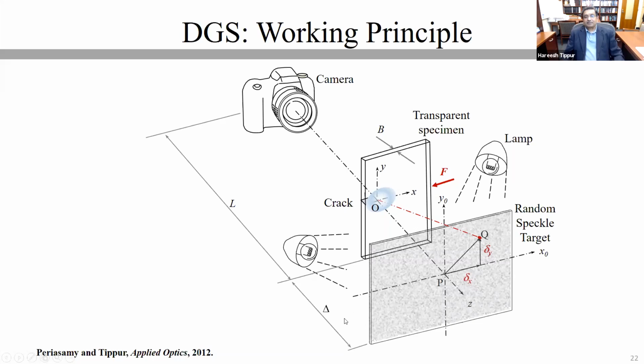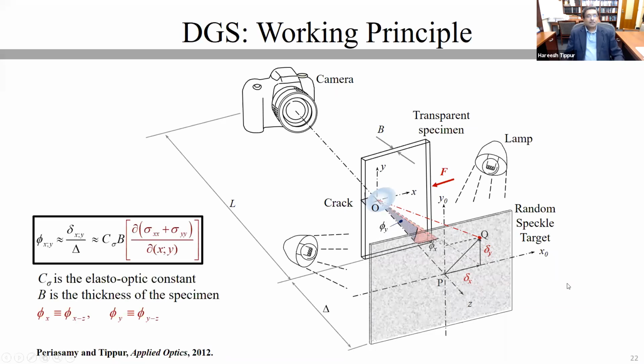I take those pseudo speckle shifts and divide that by the gap that exists between my specimen plane and the target plane. By doing that, I can get angular sweeps, phi x and phi y, that you see in my shaded area. These are the angular sweeps along the XZ plane as well as along the YZ plane, two orthogonal planes. So those angular deflections of light rays can again be interpreted as stress gradients if I were to bring in the material constant C sigma, which is the elasto-optic constant, and B, the nominal thickness of the specimen itself.